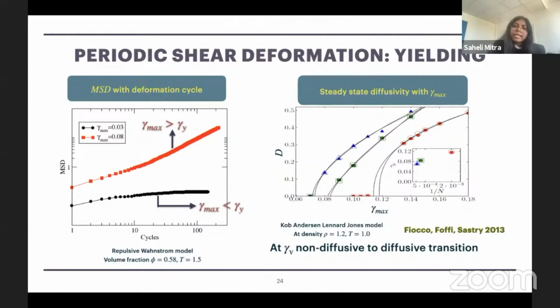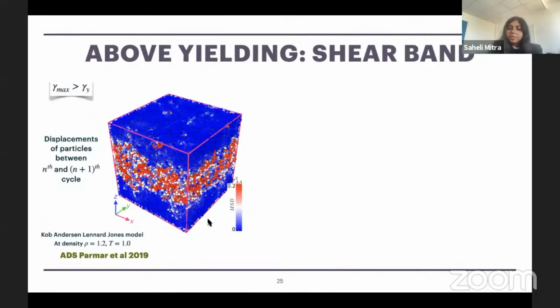Now above yielding, even though the overall system is diffusive, as it turns out, not all parts of the system move equivalently. So here is an example for a system at gamma max equal to 0.09 above yielding, where we are doing a color map of particle displacements from one cycle to the next in the steady state. And we can see that there is a band of red particles which are moving much faster compared to the other part of the system. This is actually the mobile shear band regime in the system.